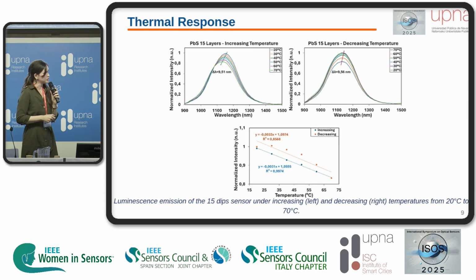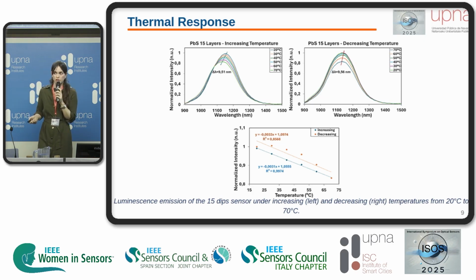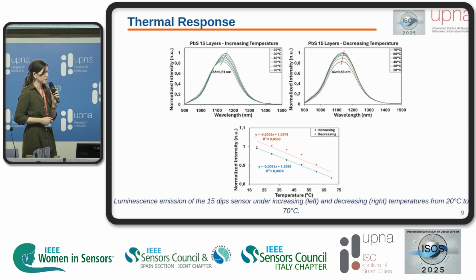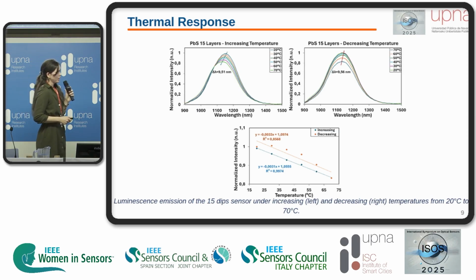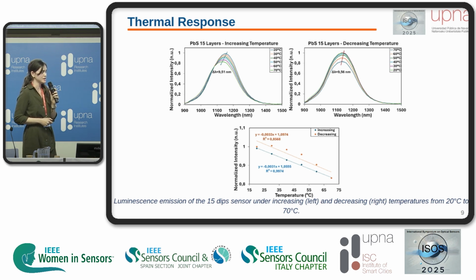Now we can see the response for the sensor with 15 dips. In this case, we also observe a response to the temperature changes. We observe the same behavior. When temperature increases, the emission intensity decreases, and we observe the blue shift. And when temperature decreases, the emission intensity increases, and we observe a shift toward the near. In this case, we observe a hysteresis, especially in the cooling cycle, and the sensitivities in this case are lower than in the case of the sensor with 12 dips.